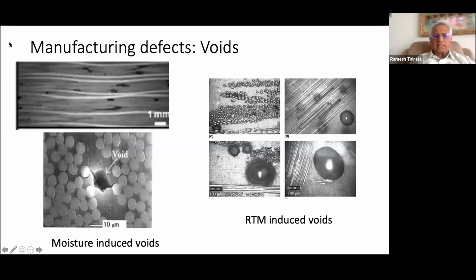And then during curing, that moisture expanded to those voids that you see as dark areas. Here you see a void, typically as air pocket trapped between two layers. And then you can see the consequence of that leading to debonding of a fiber from matrix around it. Here you see RTM because it's a low cost typically with much less control. So in some cases you could have a lot of air bubbles left over and they become essentially the undesirable void-like entities and could be causing trouble.